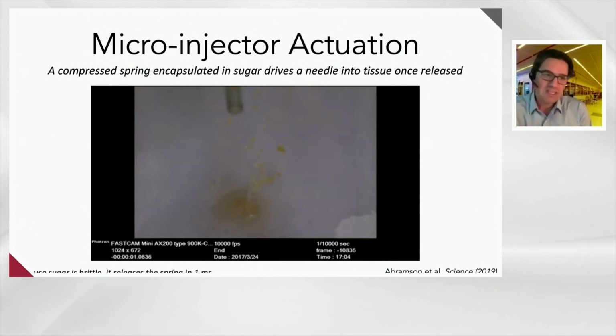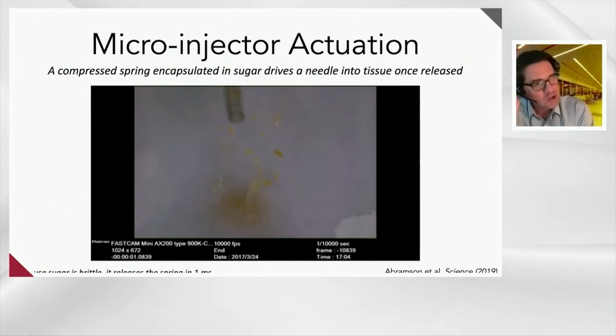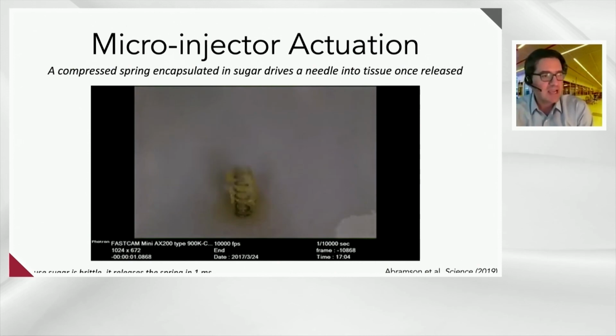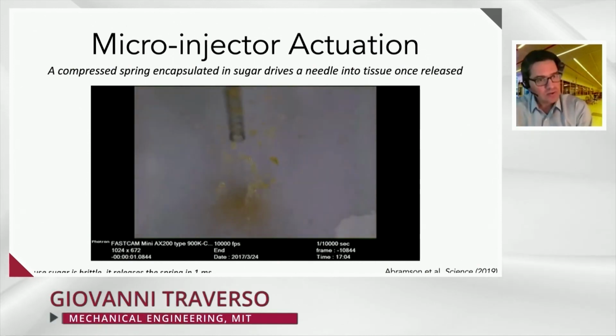And what you see here is one of those early prototypes where we encased a solid spring with sugar glass. And you see that rapid release that enables the rapid injection of a drug formulation. And we were able to demonstrate through simulation, but then also experimentally, that we could tune the time of actuation by controlling the diameter of the sugar cylinder. Now, we've addressed number 1 and number 2 in the challenge list.